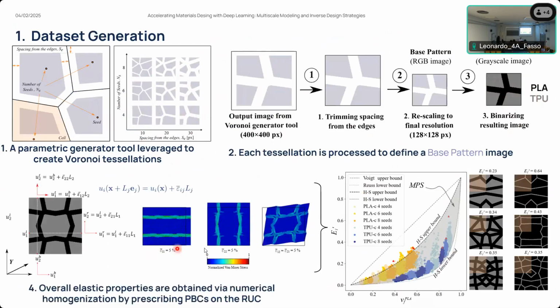And now we can, for example, represent the data set that we generated in a plane composed by the target properties, the properties that we will aim to optimize during the inverse design. If we represent all the data set in this space, we can see that there are regions of the space that have a very dense concentration of training data points, but there are other regions that are very sparse, where we have almost no training data. And these are the regions that will represent an important challenge when we try to design materials with the characteristics here, because there is almost no data for the deep learning models to extract information and reach these points.